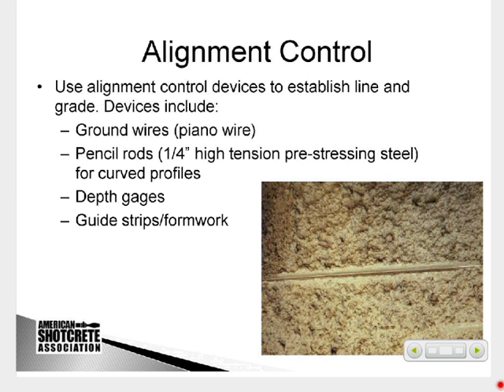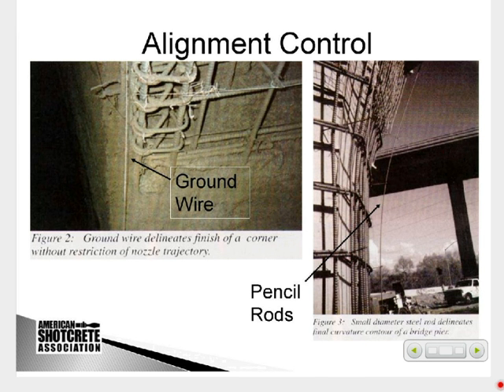Alignment control, because it is kind of a free form, we use shooting wires. These are wires that are stretched to give us the actual shape that we're going to screed to, and they allow us to give a very good tolerance. You saw the bobsled run, various things. We can get very close tolerance on the thicknesses, cover thicknesses, and overall thicknesses of the sections. We use ground wires. There's pencil rods. Depth gauges you can actually probe through, and sometimes if you have a construction joint, a water stop joint, you may have formwork that actually gives you a good gauge for the thickness.